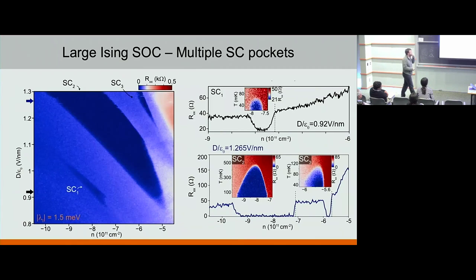And if you think about these SC1, SC2, SC3, here are some line cuts. This one is taken at this displacement field, and these two are taken at these two displacement fields. And now you can ask, how similar or dissimilar are these superconducting pockets? Good question. Yes. What are the Fermi surfaces? Do they have the same Fermiology, these 3 pockets? No, and this is something I want to discuss, that they have very different Fermiology. But before we dive into Fermiology, they also have a very different in-plane magnetic field dependence. And that's important.